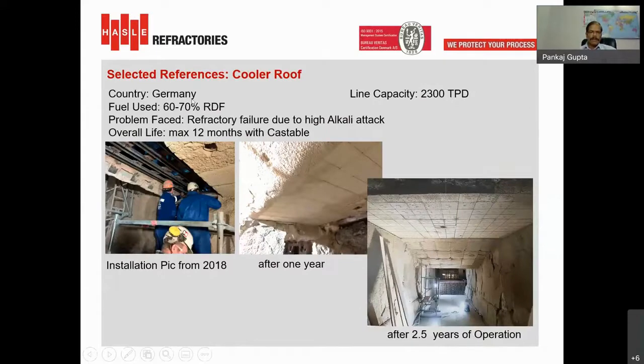This is a plant from Germany. They are using 60 to 70% RDF, and earlier they used to get only 12 months life in this cooler roof. You can see we installed our modular lining in 2018, and this is the condition after 1 year, and then after 2.5 years, the cooler roof is still in a very intact position.